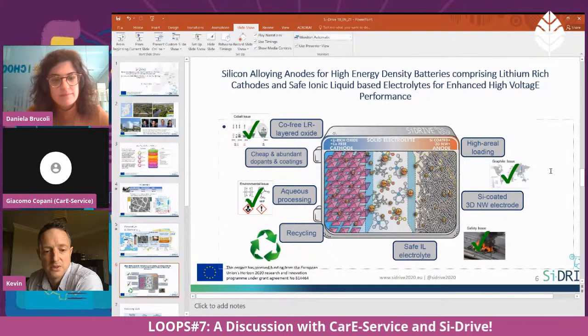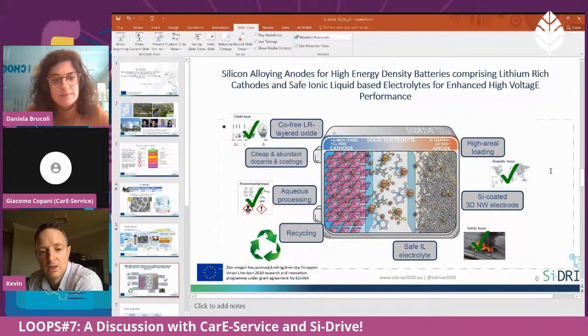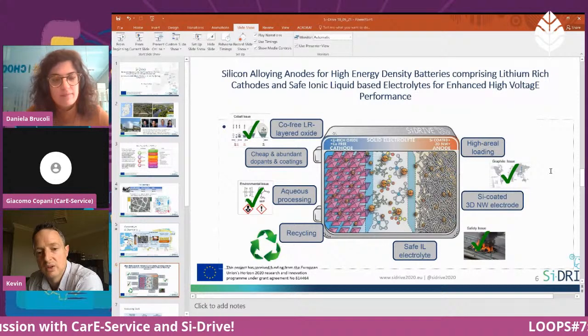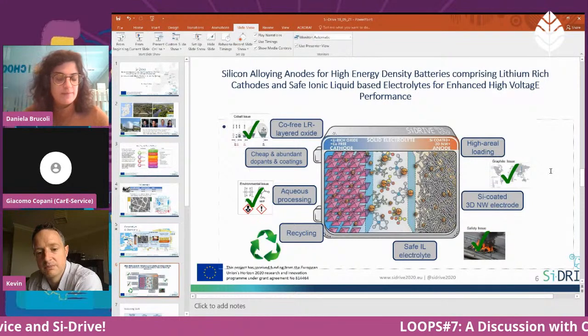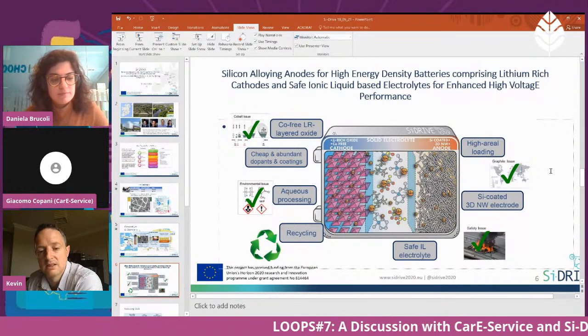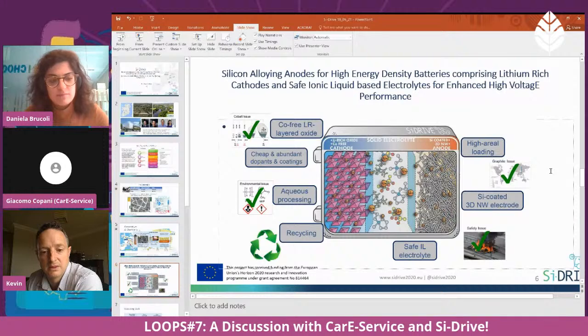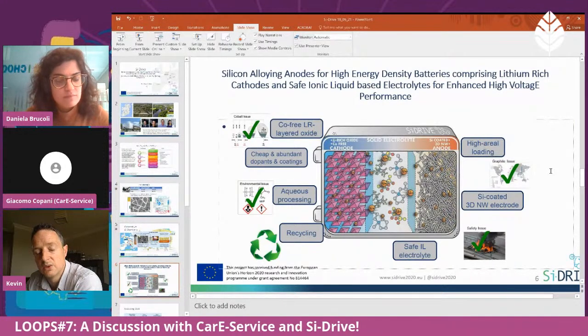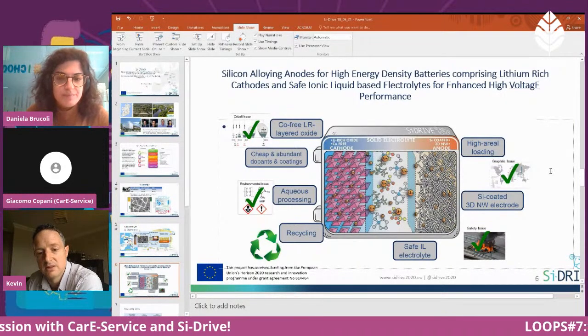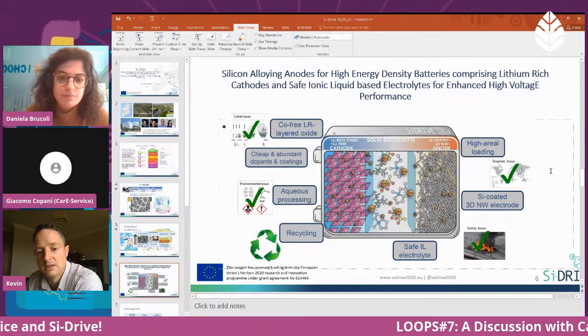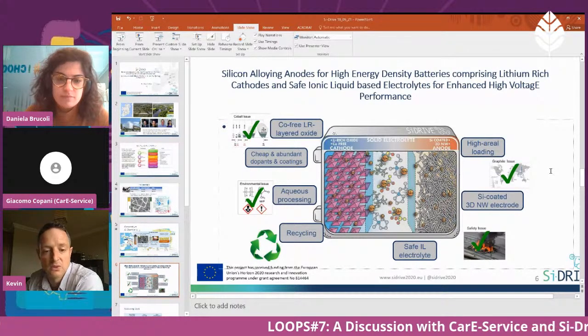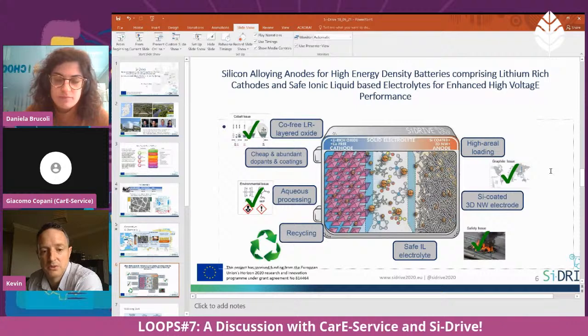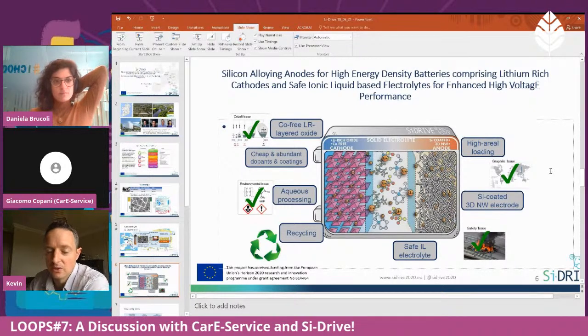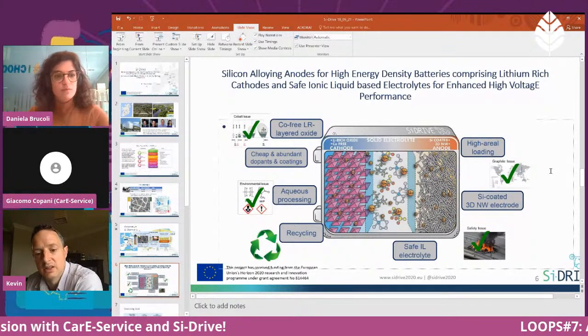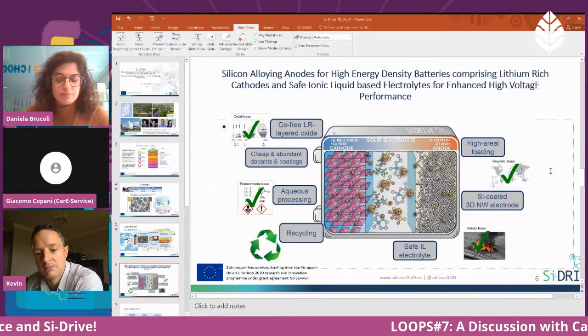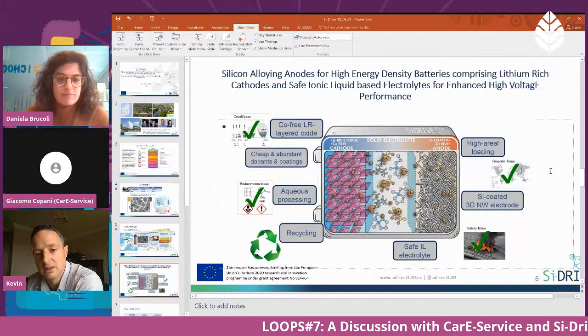So each of our components is designed from the start to make them more suitable for recycling. So we're building that right into the start of the battery configuration. The ionic liquid electrolyte is a lot safer than the organic electrolyte. So in the event of a crash where you get a piercing of your battery cells, the risk of thermal runaway is a lot lower, as the flash point is significantly higher than it is for the organic solvent. So it's a much safer chemistry for use in electric vehicles.